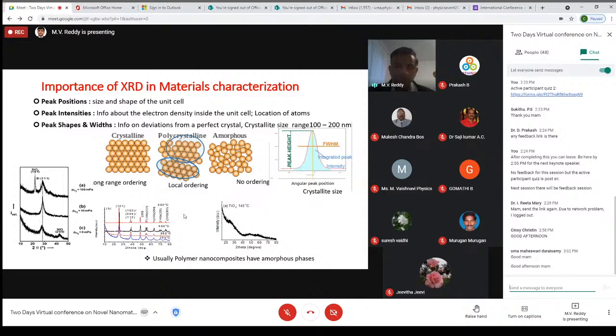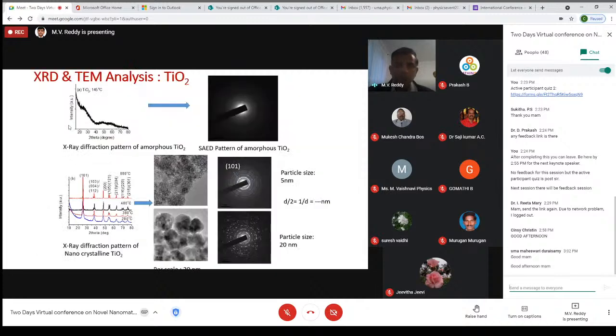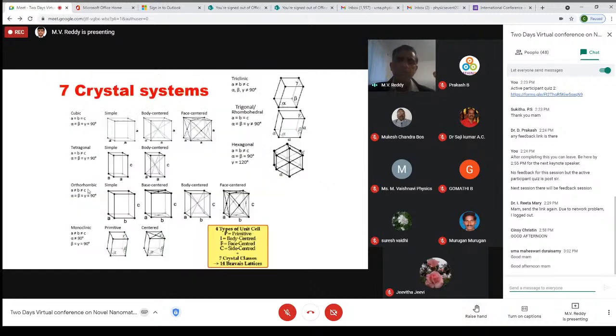So as you can see, for example, this is a typical amorphous sample. Complementary to TEM, you can see no lines. If it is nanocrystalline, we get a circular ring like that. For improved crystalline, or polycrystalline, you can get dots. Then we usually use the diameter divided by 2, and 1 over d. So this d value we can closely compare to the XRD. That's the way we are going to index these particular things.